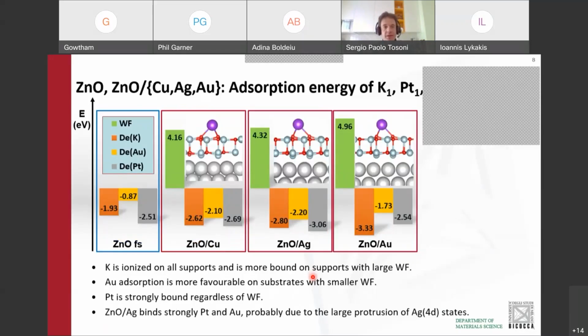Moving to ZnO supported on copper, silver, and gold, we notice that the work function of the system increases when you go down the group. So it is 4.16 eV on ZnO on copper and becomes 4.32 electron volts and 4.96 electron volts on ZnO supported on silver and gold respectively.